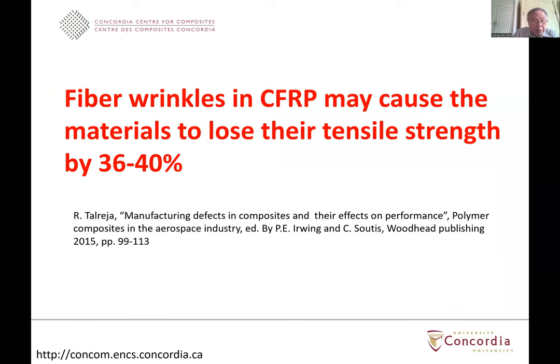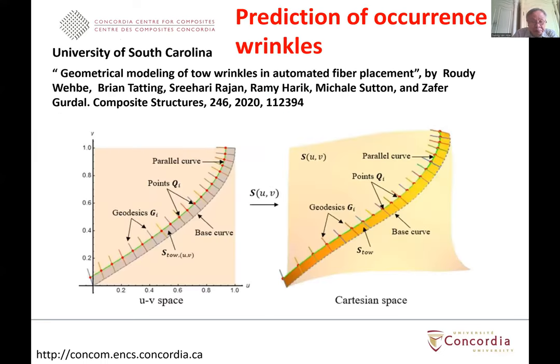Now, there was some work done in 2015, and they mentioned that the presence of these fiber wrinkles in the CFRP may cause a loss in tensile strength of between 36 and 40%. This case is very critical. I mean, there's a lot of loss. So that means people are trying to reduce the wrinkles and to understand the wrinkles, and much work has been done.